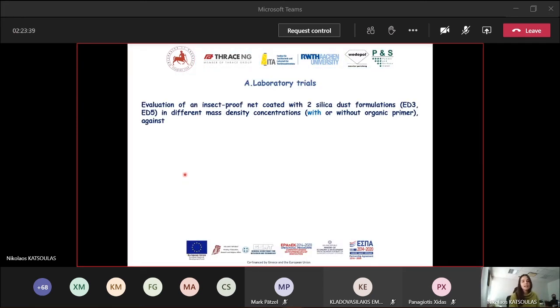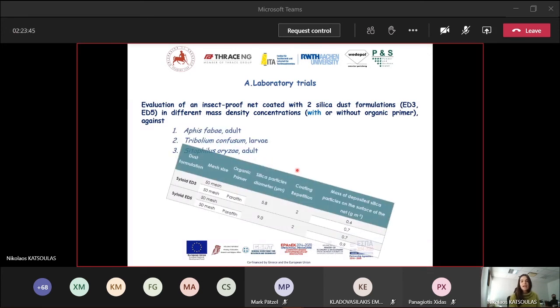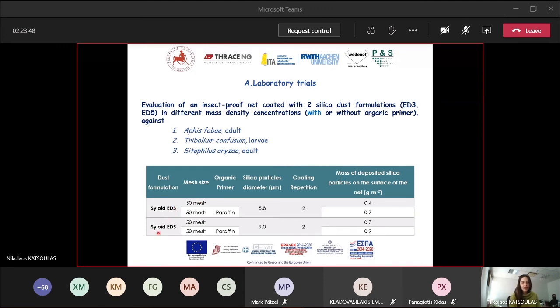To begin with the laboratory trials, we first evaluated an insect-proof net that was coated with two different dust formulations, namely Syloid ED3 and Syloid ED5, in different mass density concentrations against Aphis fabae, Tribolium confusum, and Sitophilus oryzae. In two of the four treatments, we also added paraffin as an organic primer on the net surface in order to increase the mass of the deposited silica. It's pretty important to note here that all nets had the same mesh size, which in this case is 50 mesh.